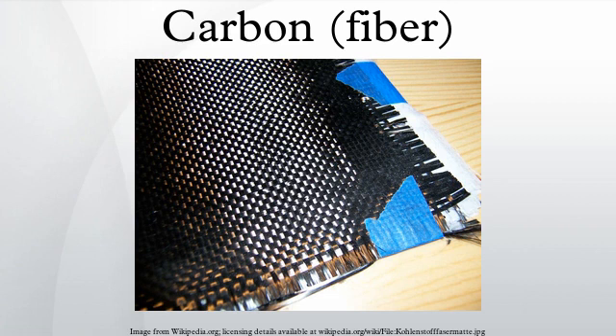Carbon fibers derived from polyacrylonitrile are turbostratic, whereas carbon fibers derived from mesophase pitch are graphitic after heat treatment at temperatures exceeding 2200 °C. Turbostratic carbon fibers tend to have high tensile strength, whereas heat-treated mesophase pitch-derived carbon fibers have high Young's modulus and high thermal conductivity.